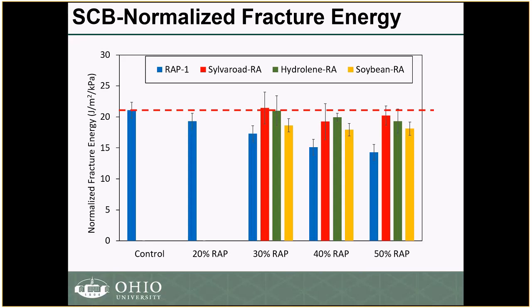If we're using the right recycling agent, in this case the Sylvaroad and the Hydrolene, it seems that up to 50% RAP, we will be able to still maintain the fatigue cracking. Very important is the RAP binder replacement, something that I will be talking about in the second phase. The maximum that we had was 41% for the 50% RAP. This is how much of your total binder was replaced by the RAP binder.